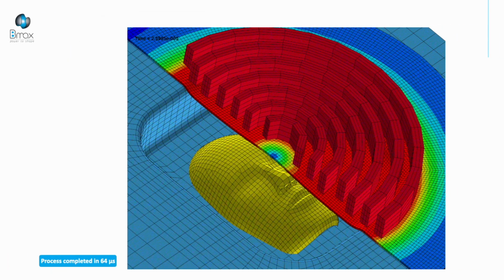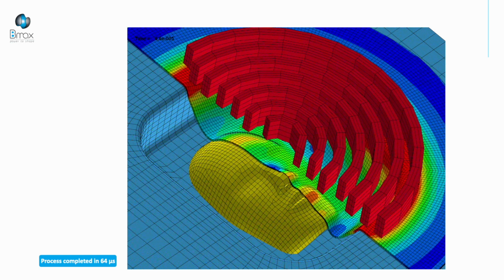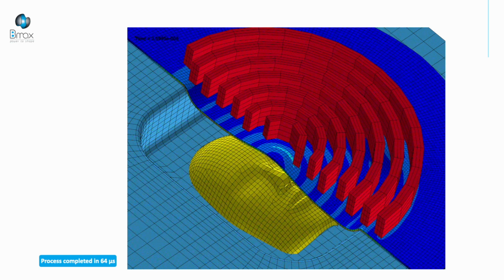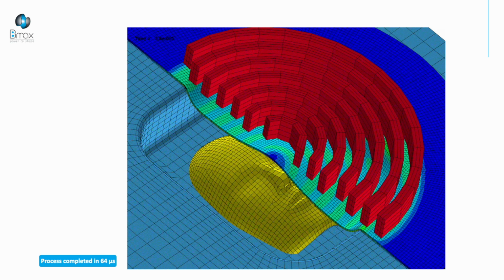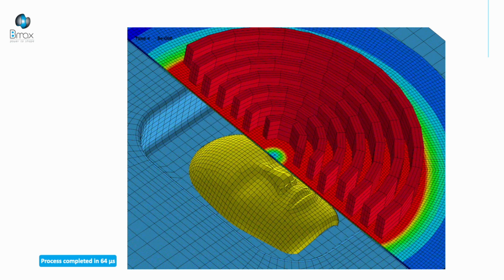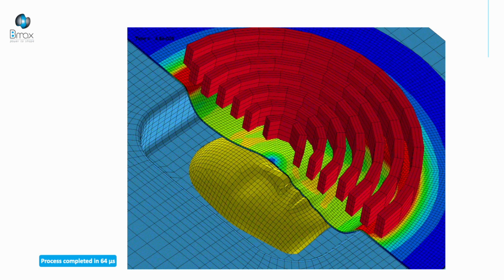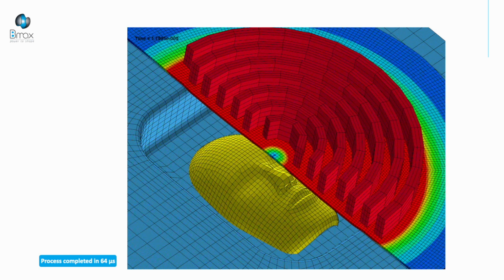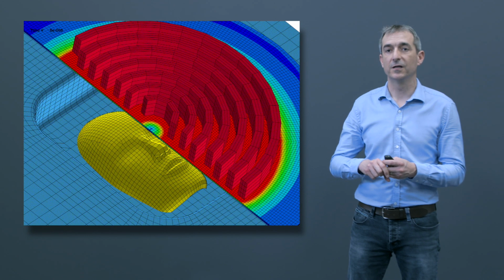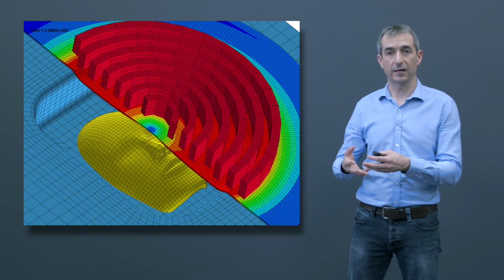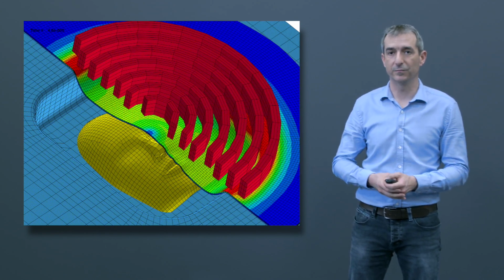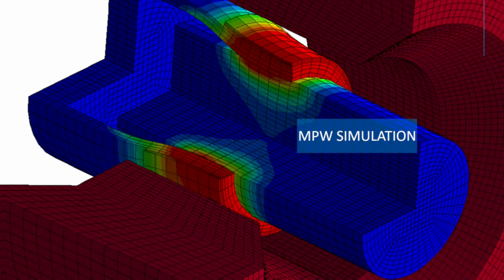In this example, we applied the pulse current directly on the coil, the red component on the screen, and the coil creates a magnetic field and pushes the flat blank to the bottom of the die. The fringe, the color, represents the maximum of Lorentz force. All the process is done in 64 microseconds. As you can see, the maximum of Lorentz force depends on space and time. That's why we perform this kind of coupling between all these solvers.